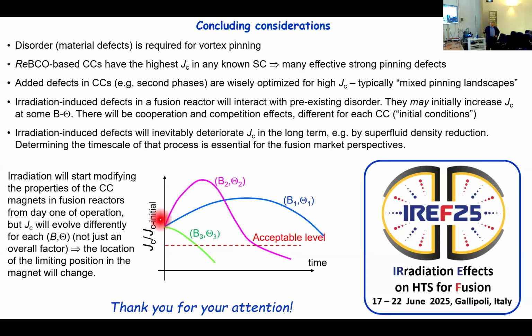This is a cartoon showing that, for instance, we have three different locations in the magnet where the field has different values and different orientations. So it may happen that in one of them, initially there is a very large increase. But this is not particularly good because you need the magnet to operate from day one. You cannot rely on the future increase. But anyway, it will buy you some time and eventually it will start to deteriorate and go below the acceptable level. In some other location, the increase may be smaller, but deterioration will be slower. In some other case, there may be no improvement at all and a fast deterioration. The reality of this cartoon is what the community needs to figure out for each coated conductor to be used in each magnet of each fusion reactor.